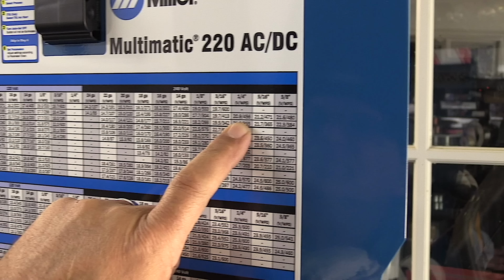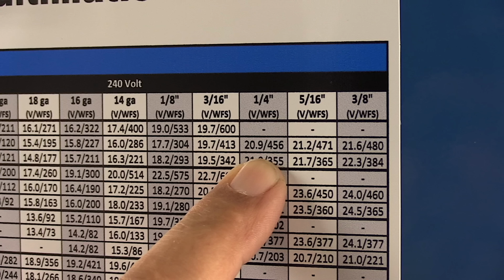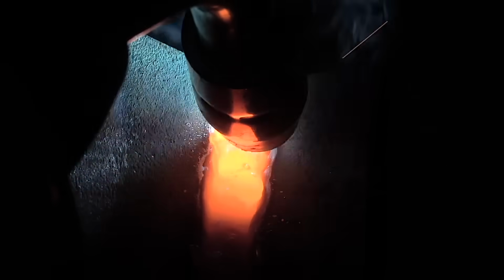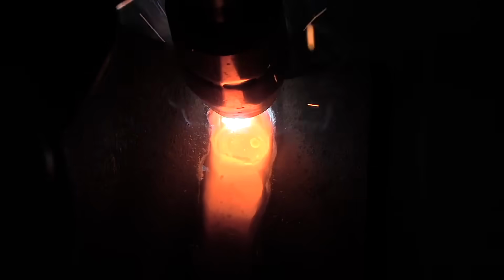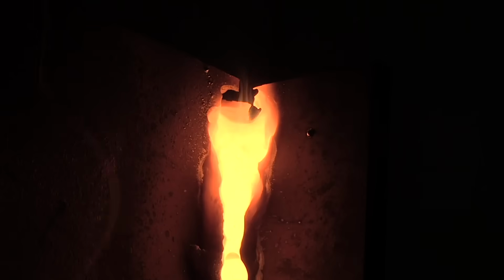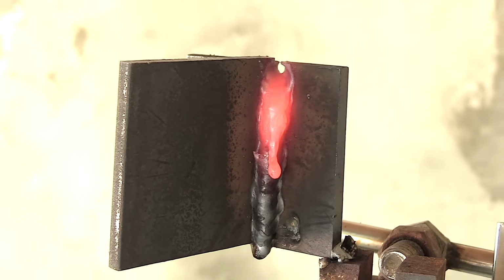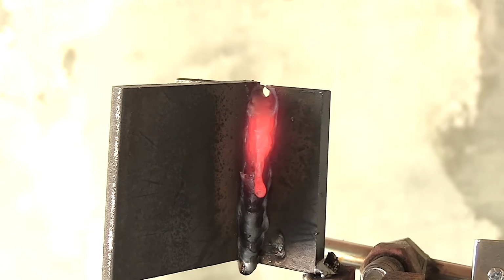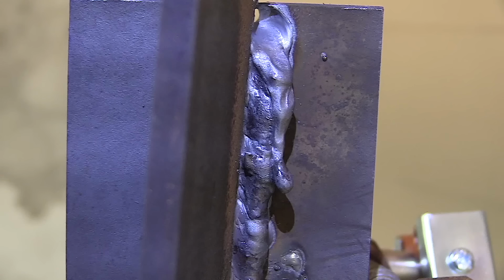Now, again, those settings recommended for 1/4 inch are super hot. If you try to weld uphill with that with short circuit MIG, unless you're way better than I am, you're going to have a problem like this. It's so hot going uphill, it just wants to run out with you.